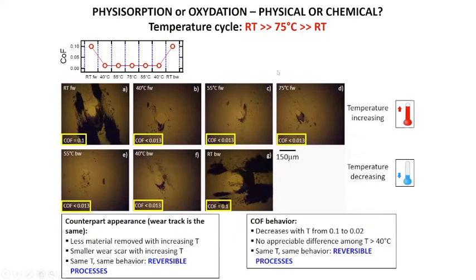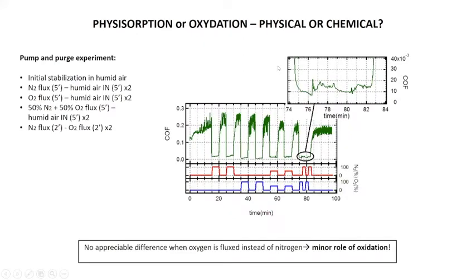But the final test, which represents more or less the smoking gun about this topic, is reported here, and it is what we call the pump and purge experiment. So we measure again the coefficient of friction as a function of the cycle of time. But in this case, we change in real time the condition of the sliding, of the ambient. So we started the measurement in presence of humidity here, and you can see that after some time you reach the steady state at 0.2, and as soon as you induce the flux of nitrogen here, you have the decrease of the coefficient of friction to more or less 0.01 or 0.02, as already observed.